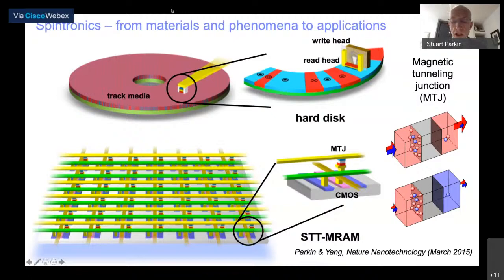Depending upon the orientation of the magnetization of the 2 electrodes, the electrons can tunnel very easily to give a high conductance when the moments are parallel, or when they're anti-parallel, then the conductance can be reduced. And we showed that at room temperature, you can achieve changes in conductance of more than 200%, which is 10 times higher than the largest magnetoresistance developed by a spin valve sensing device. However, the basic structure of the tunneling junction device that is used in magnetic disk drives is very similar to the spin valve device. It's just a replacement of a copper layer with a magnesium oxide layer.